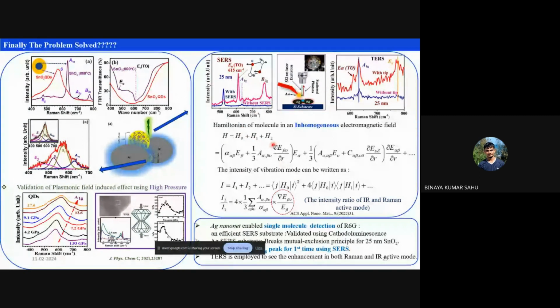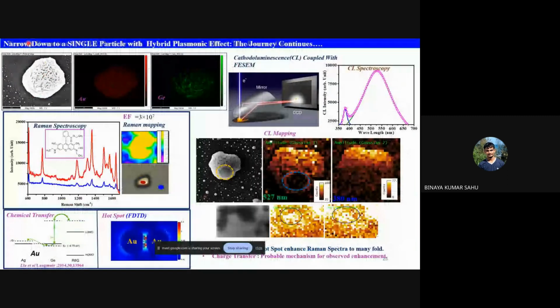And there is a very important and very interesting theory, for those who have started using quantum mechanics, they could understand this part. Here basically what you are doing, you are perturbing your material by keeping it in an electromagnetic field, and you do some bracket kind of mathematics. And if you don't want to go to the complexity of this calculation, the take-home message is that I2 stands for the intensity of the IR peak, and I1 stands for the intensity of the Raman peak, and that is directly proportional to the electromagnetic field gradient. So because of that, I2, the IR peak, could be enhanced when you are doing the Raman spectra. So finally, the problem was solved, it seems.